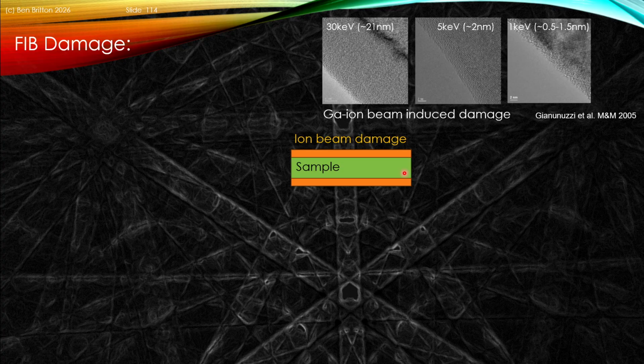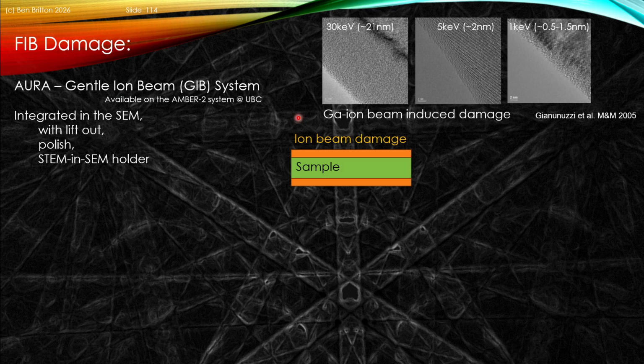Now, this would be using a gallium probe. You can also use some other methods, and one of the exciting aspects that we're getting at UBC is the Orsay Physics gentle ion beam system, and so our Amber 2 gallium FIB will be equipped with a gallium probe, focused ion beam, but also a broad ion beam that has an argon ion system.